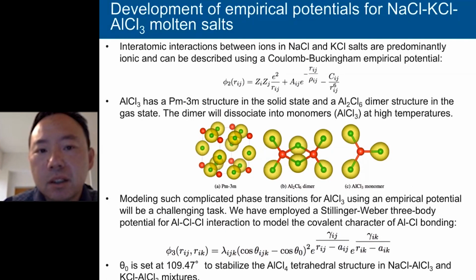During the development of the interatomic potentials for these sodium chloride, potassium chloride, and aluminum chloride molten salts, I used the Coulomb-Buckingham empirical potentials to describe the interactions in sodium chloride and potassium chloride, which are predominantly ionic in nature. Aluminum chloride, on the other hand, has very complex bonding behavior. At low temperature, it's in the solid state and has a cubic crystal structure, where each aluminum is surrounded by chloride, forming a 90-degree angle, as shown in the left figure.